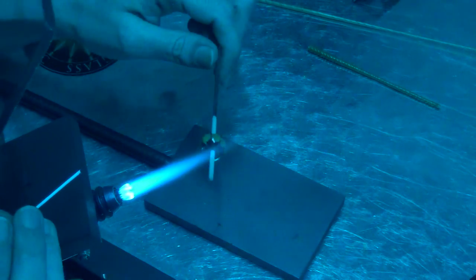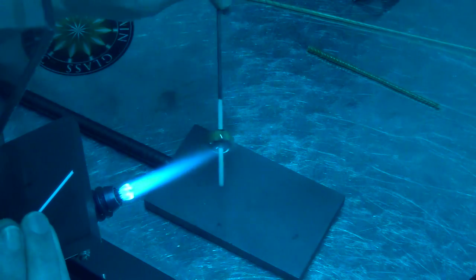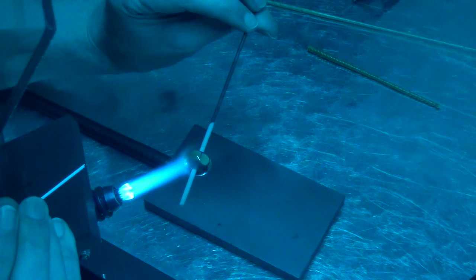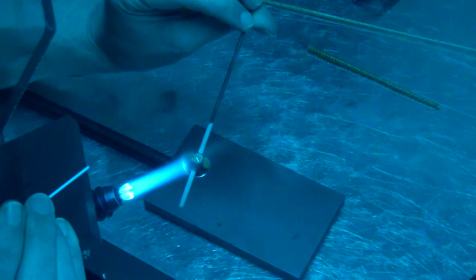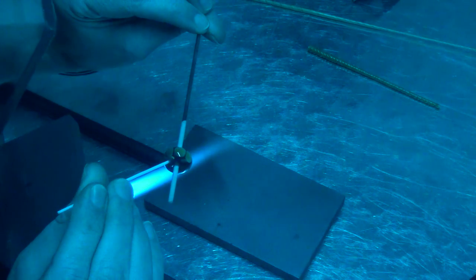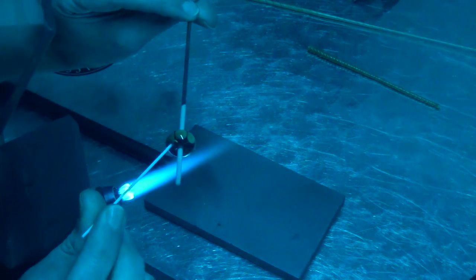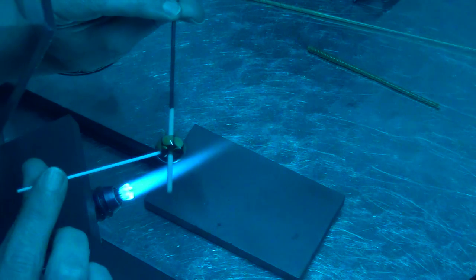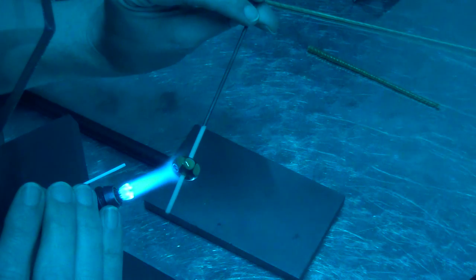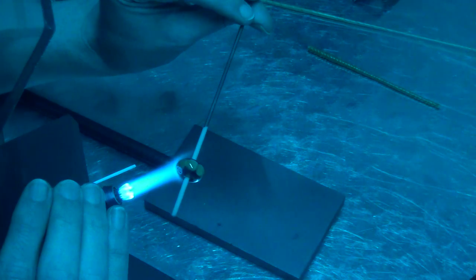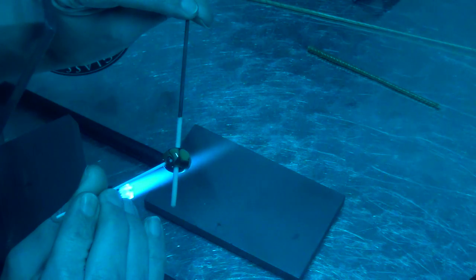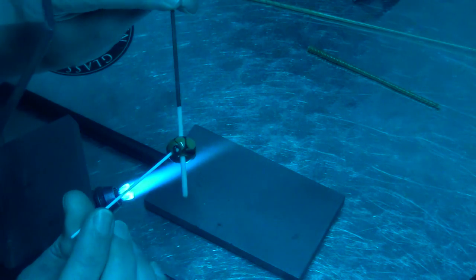So step two is to basically twist all these dots. I'm heating up the area in between the edge of the two dots, kind of where the two humps come together, and then I stick the stringer in, twist a little bit, wait, and snap it off. Now you want to do this all in one motion kind of, but you want to also have it be discrete steps. So you stick down, twist, break it off.